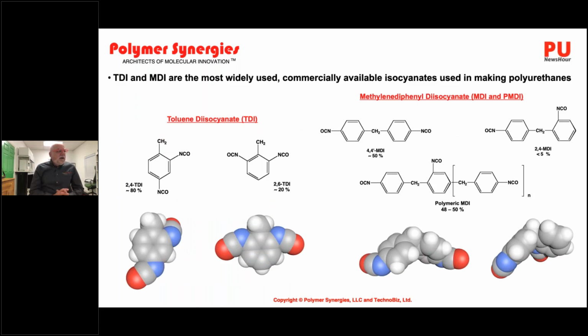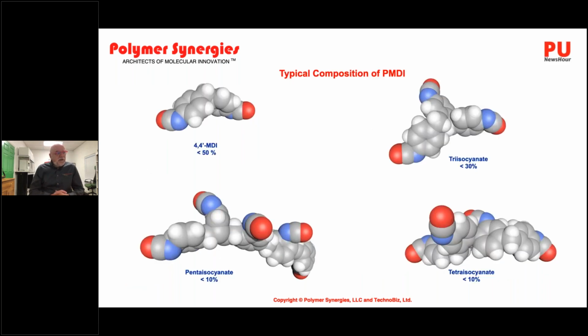These are the 2 most common aromatic isocyanates used commercially: toluene diisocyanate, which usually is sold as a mixture of 80-20, 2,4 and 2,6, and then MDI and polymeric MDI. 4,4 MDI or pure MDI is this structure here, and polymeric MDI is a mixture of oligomers that you see in this particular slide. I'm going to show you the composition of PMDI in this slide, and about 50% of the PMDI that you buy is 4,4 MDI, and the rest of it is higher oligomeric species, like triisocyanate